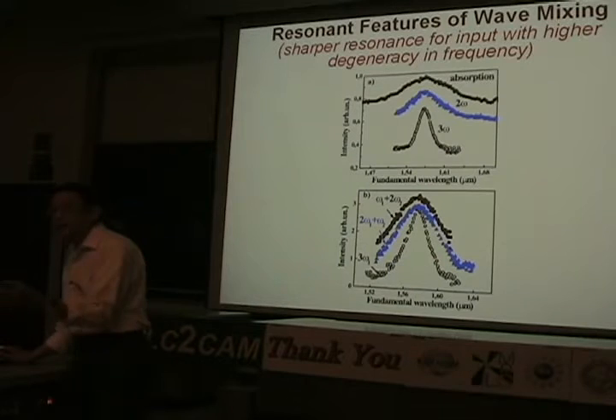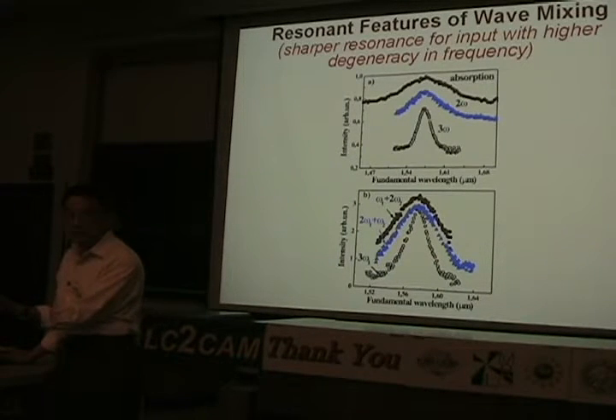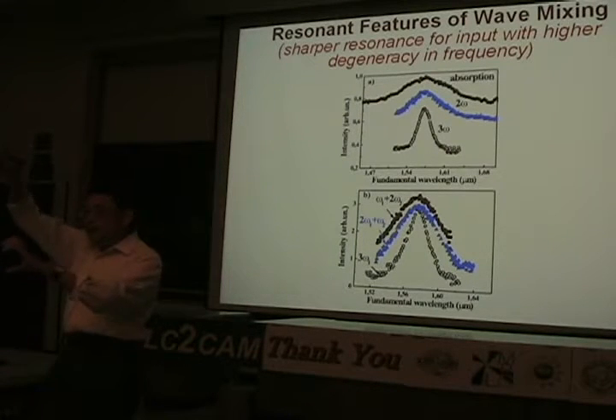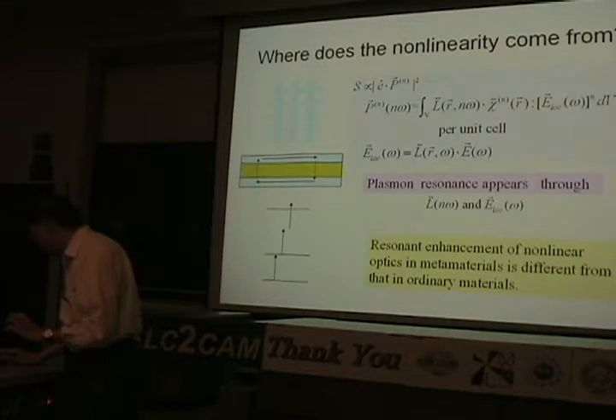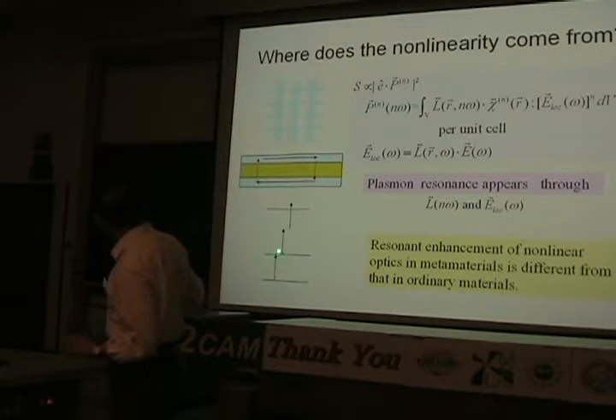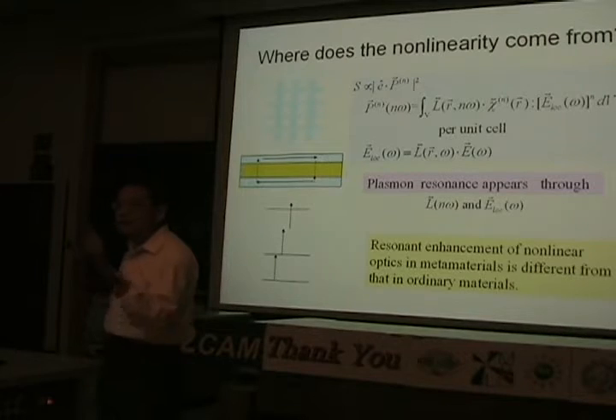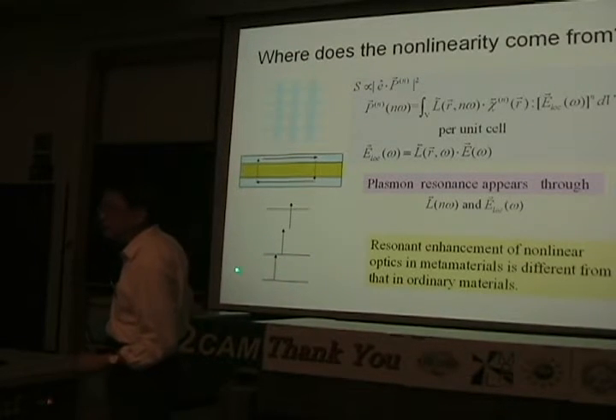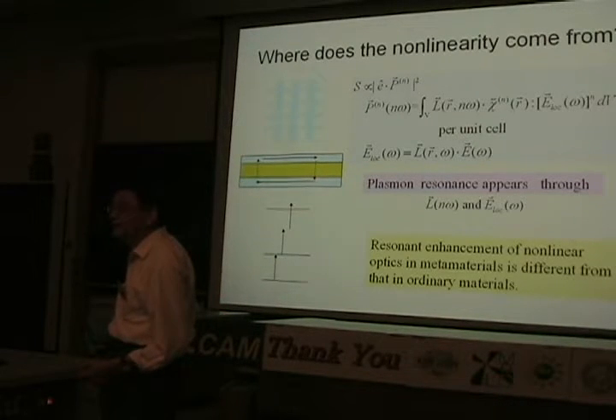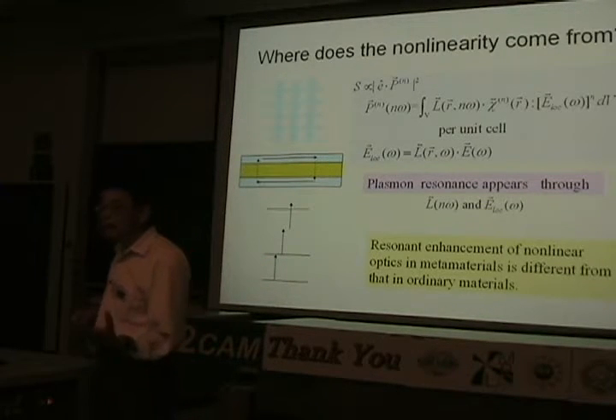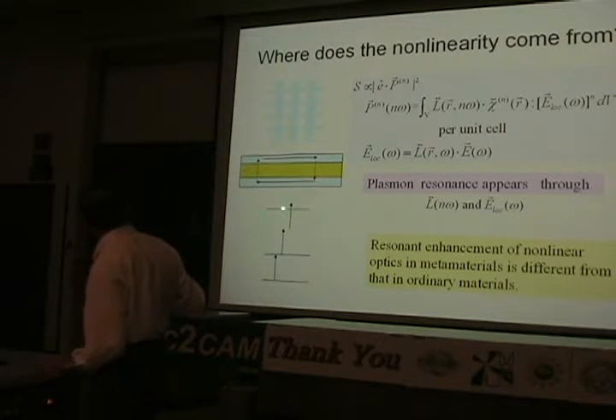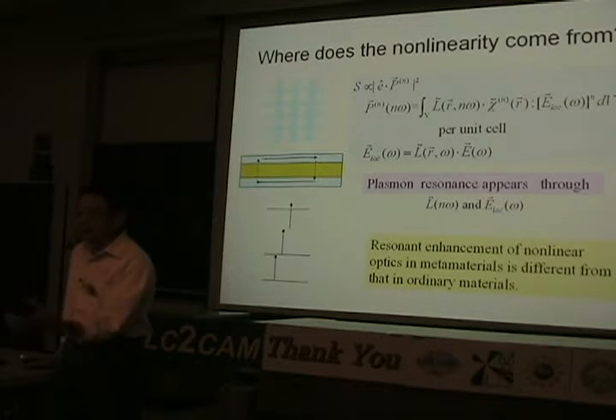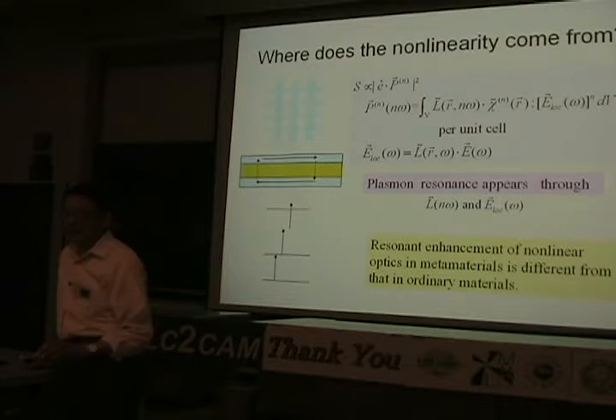Now, I started by saying that these nanostructures can be considered as atoms or molecules. If you think that way, then you would say, if I have an atom or molecule, I have all these energy states. Okay? So if I have all these states, if I have omega 1 on resonance, then all the other excitation will not be on resonance. So I have only a single resonance, right? So whether it's second harmonic generation, or third harmonic generation, or wave mixing, I only have one resonance. Right? I don't have double resonance in the molecular case or atomic case. But in our case, it seems to suggest that for the 3 omega third harmonic generation, I have triple resonance. That's why it becomes sharper.